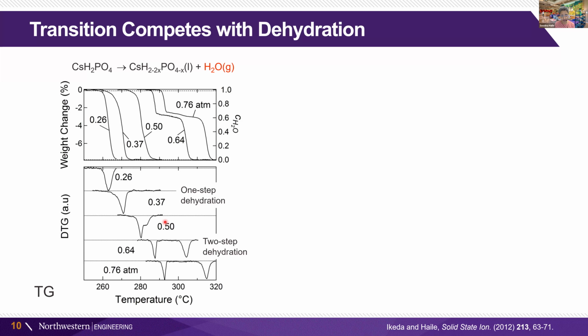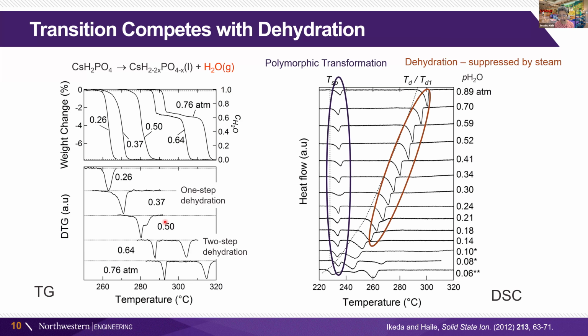Now, if you compare that to the DSC signal, the differential scanning calorimetry behavior, you can see that there is a transition that is insensitive to the steam partial pressure, followed by a transition that depends on the steam partial pressure. So we identify the first one as being the polymorphic transition because that should not depend on how much steam is in the system. It's a solid, fixed composition transition, whereas the dehydration, which we saw already in the TGA experiment, is indeed suppressed by steam.